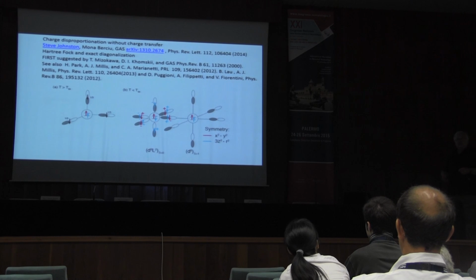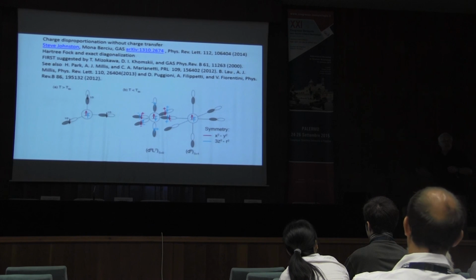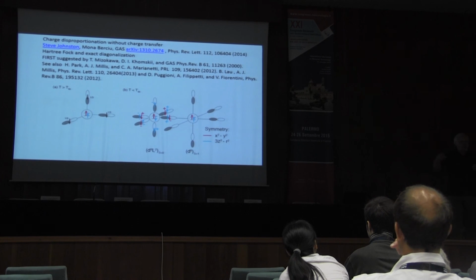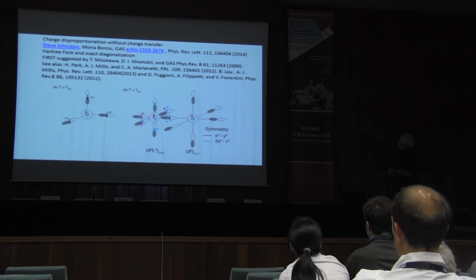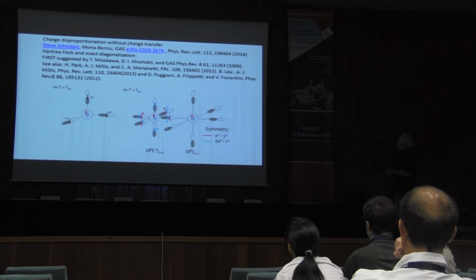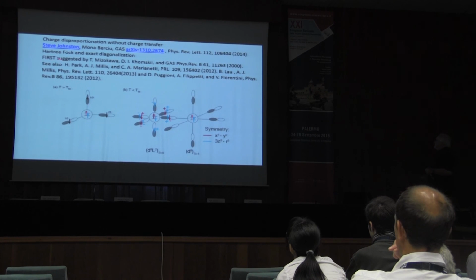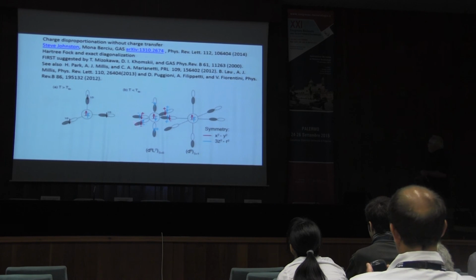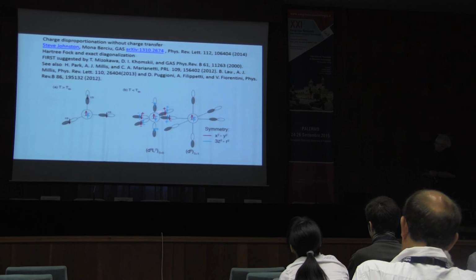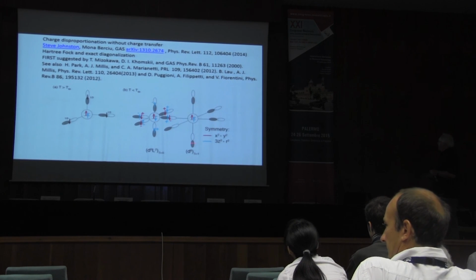Actually, I should say that we know that there's a phase transition. The semiconductor-metal phase transition is a transition in which you get this doubling of the unit cell, or you have this half superlattice structure, which corresponds exactly to these compressed and elongated octahedra. So doing a calculation of exact diagonalization and Hartree-Fock, Steve Johnson was the main guy who did this, we showed that it's not really charge disproportionation that is occurring, it's bond disproportionation, where you get these short bonds and you get these long bonds, exaggerated